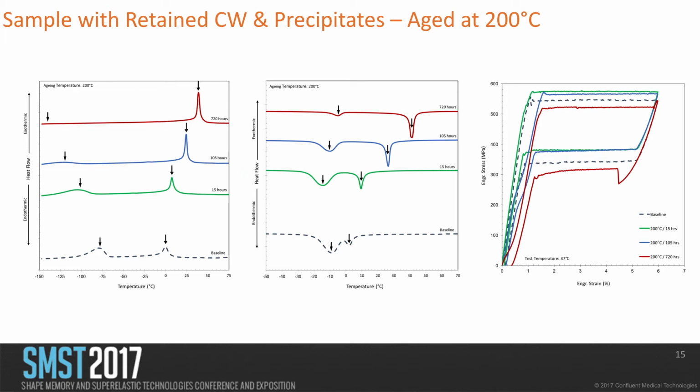Now at 200 C, suppression is there again. The R phase is becoming more and more stabilized at higher temperatures. And the mechanical properties, the plateau stresses go up and then come down again. And I'll talk about this in a moment, why that is.